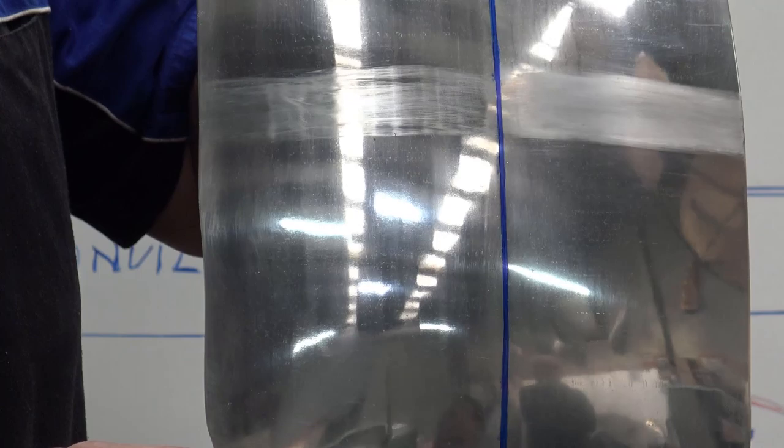Then I literally took this panel out, adjusted my wheel using the counter lever, so I did not move the pressure. And I've done one on the flat wheel. High pressure, a little bit wider than this one. But guess what? When I put the same pressure back on with the flat, nothing happened. Look at it, there's nothing there. Which means that you'd have to squeeze further to achieve anything. So when you do squeeze further, that's when you get your lines. That's why the flat there is no good.